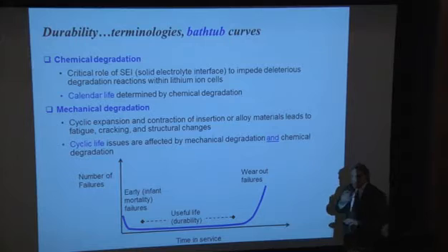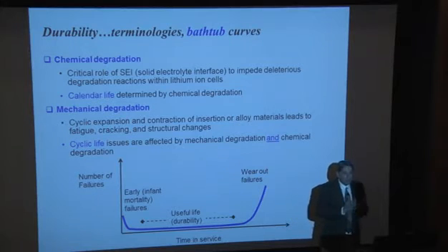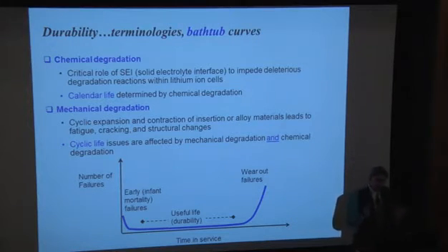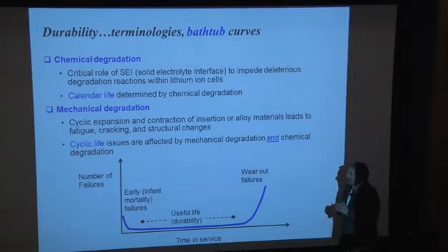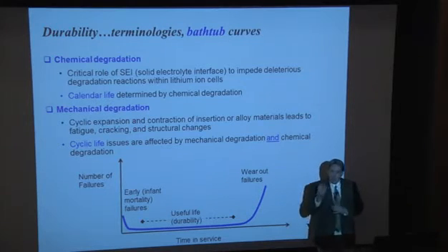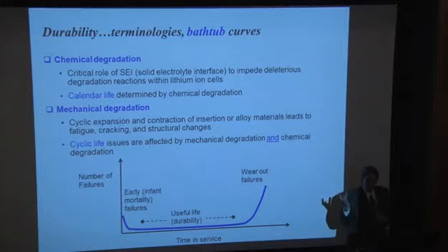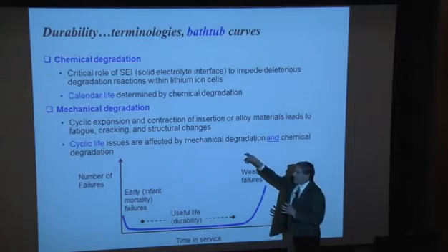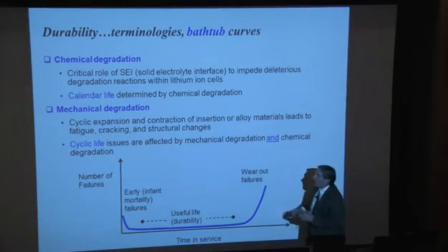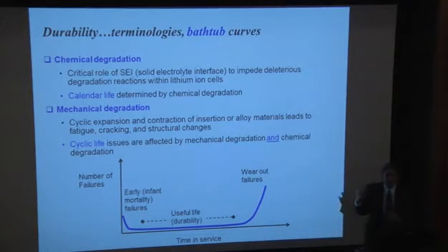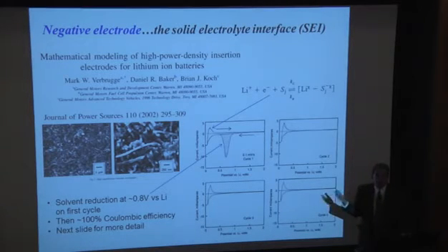Now, you can, loosely speaking, try to deconvolute these processes into saying calendar life. That's a chemical degradation reaction, which I'll talk about. So if the battery just sits there, it's going to chemically start to degrade and consume some lithium. And then you have cycle life, and this gets into the expansion and contraction, formation of cracks, new surfaces. They get passivated by the chemical reaction from up above, so it is coupled in that respect. But you can argue that mechanical degradation is nominally related to cycle life more than calendar life. Obviously, if something's just sitting there not cycling, you don't have a cycle life dependence.